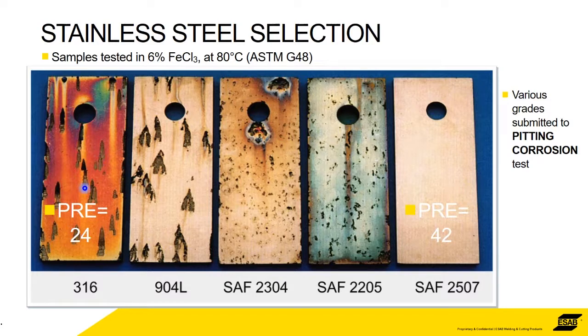And pitting corrosion is a bit like an iceberg. The damage is all underneath the surface. So this is in a very bad way. Compare that with, say, a lean duplex. You can see there's been some effect there. There's a lot of pits. The whole surface is discolored. Standard duplex is a little bit less. This is super duplex, 2507 super duplex.